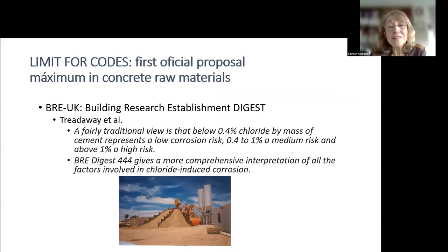Well, this early work finished in a digest from BRE that was written by Ken Treadaway, and I think Everett as well, and he said that the fairly traditional view is that 0.4% chloride by mass of cement represents a low corrosion risk, from 0.4 to 1 a medium risk, and above 1 a high risk, and they repeated it in other digests. I also met Ken Treadaway at that time, and he said 0.4, and